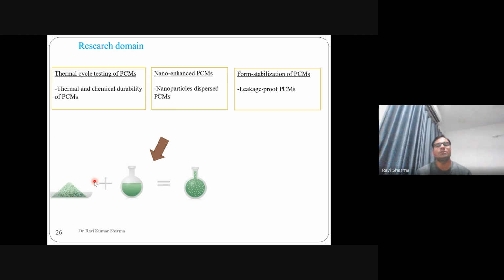For enhancing the conductivity, we need to add some foreign particles into the PCM. Adding nanoparticles is one of those ways. We melt the PCM and the nanoparticles are added into the molten PCM. That's how the nano enhanced PCM gets developed. The white spots you see are nothing but the nanoparticles. But one thing to notice is that when we add nanoparticles, the dispersion should be uniform. Otherwise, nanoparticles have a property to sediment and agglomerate. They come toward each other and form a cluster. That shouldn't happen, so to break the cluster there is a way we use: we add some more material so that the cluster and agglomeration don't happen. That has to be avoided.